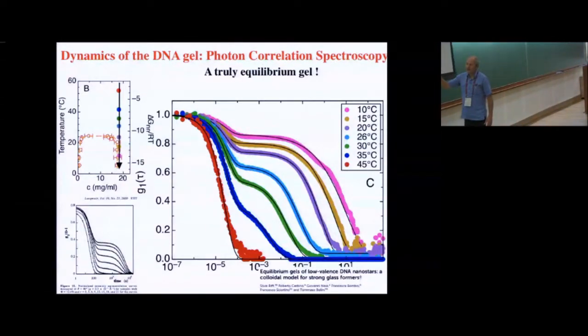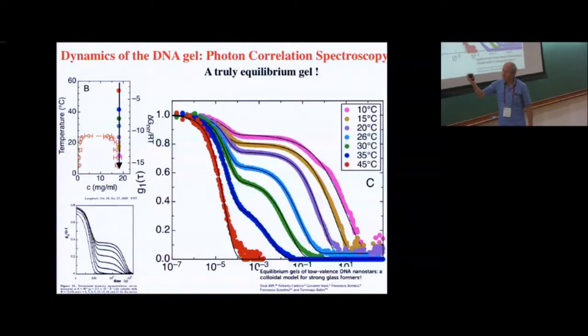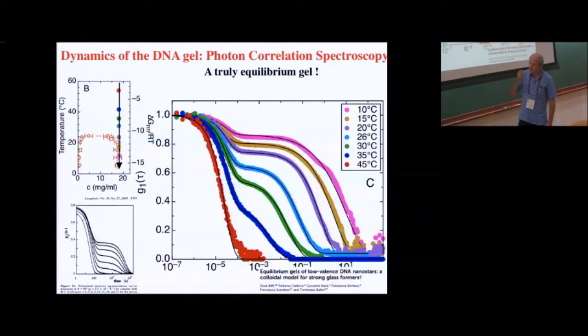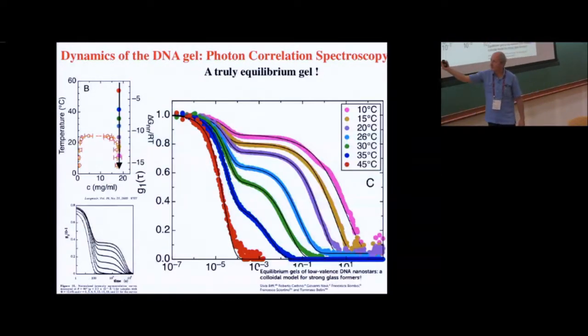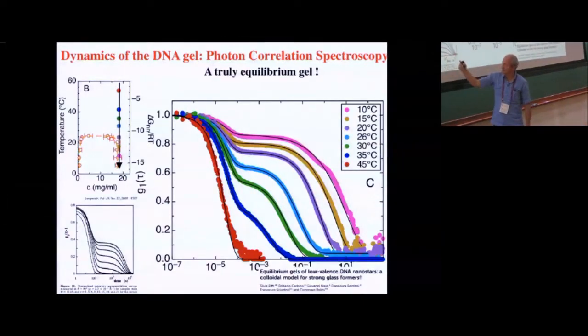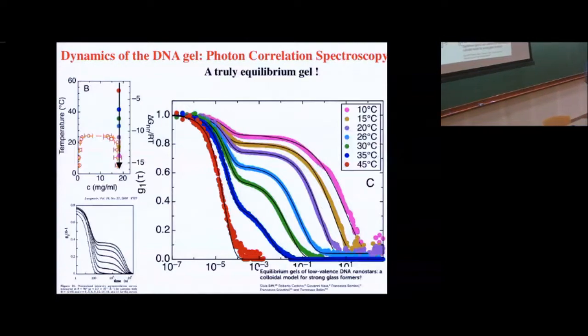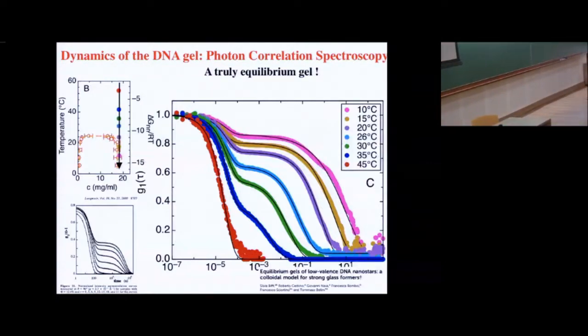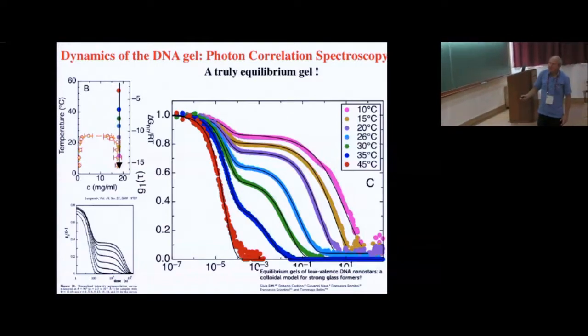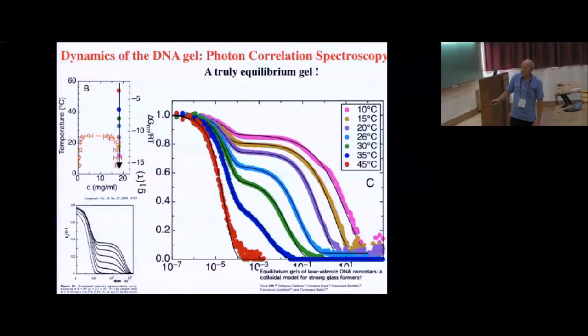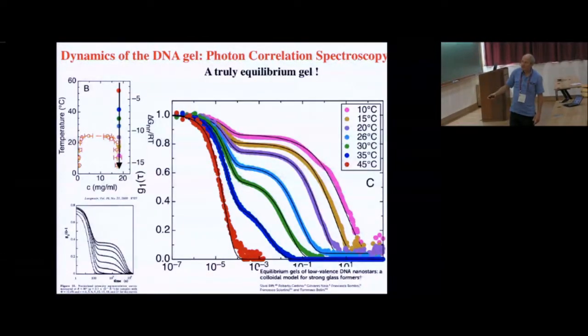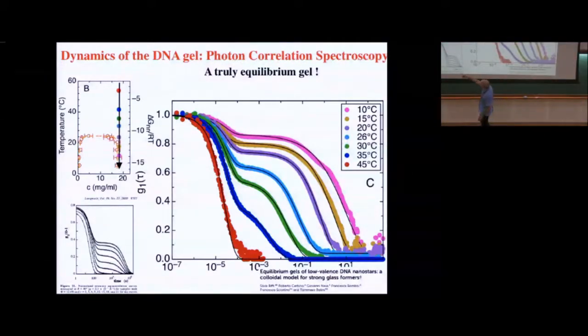There were not many experiments on the behavior of the density fluctuations in a gelling system. But one that I want to remind you of is, again, the system we discussed in the previous lecture, the telechelic polymers, right? Again in Montpellier. And this system has a very similar behavior. You see that the plateau height goes up as you increase the number of polymers that we put in the system, the number of bonds that we put between the oil droplets. We see this increase of the plateau.